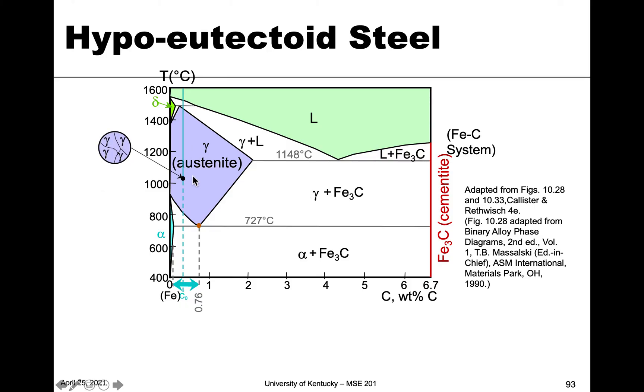So if we're up here and we have austenite, that basically means that all of the carbon in the system is soluble in this phase of iron. Just for your information, that's a FCC phase of iron. So FCC iron has all of the carbon soluble in it. However, when we start to drop in temperature, we see that the solubility goes down and therefore we're going to have to start to form alpha and then some form of carbon, which in this case is the cementite. So Fe3C.